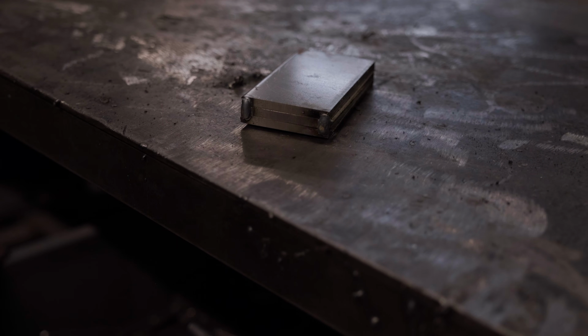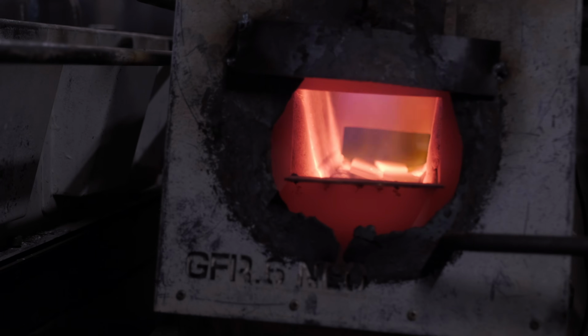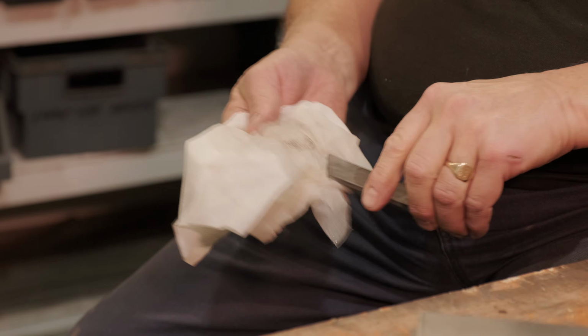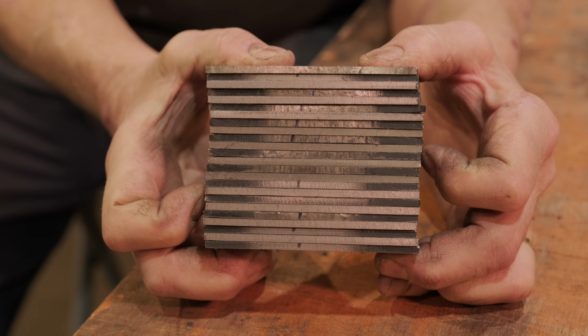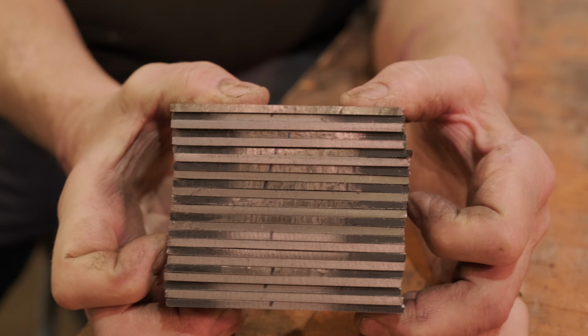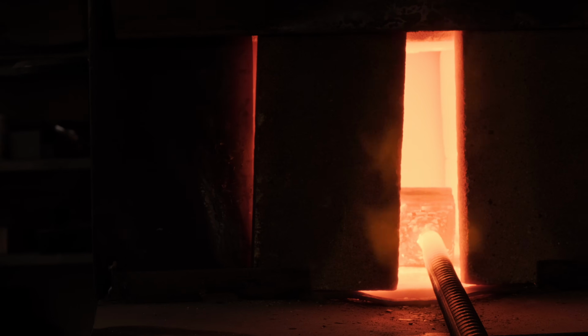So therefore we come back to saying, right, well, I've now got a stack of Damascus all tacked up. It's in my forge getting nice and hot. I need to forge weld it together. So the first thing you need is you've got to keep those surfaces clean. Preparation is something we'll come to in a minute, but let's just get past the actual forge part first. You've got this stack of metal all nice and clean, and you've tacked up the edges and you want to get it hot. You've got to make sure you don't start oxidizing those surfaces.